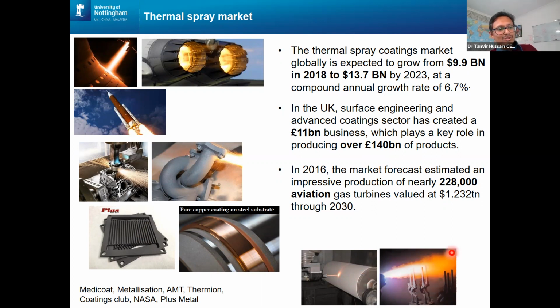And when we go through hip replacement, knee replacement, or anything which goes inside our body, those components are also coated with a bioactive coating, either with titanium or hydroxyapatite. So the coatings are almost everywhere. In the UK, the coating sector is 11 billion, and it plays a key role in products over 140 billion. In terms of gas turbines, we have an impressive production of around 228,000 aviation gas turbines, and the market value for that is around 1.2 trillion. The numbers give you some idea of how significant coatings are for operation of these components.